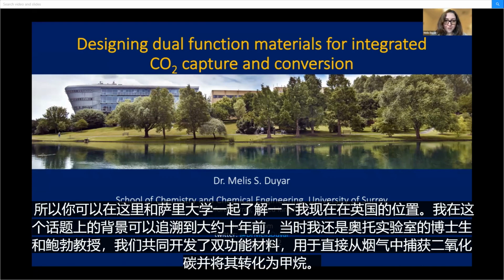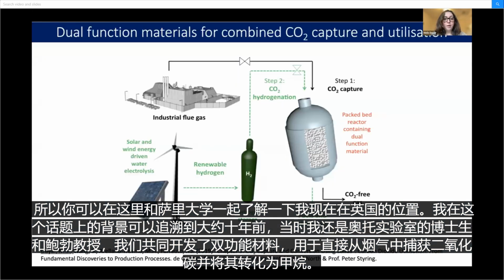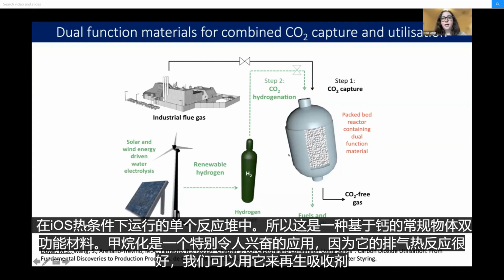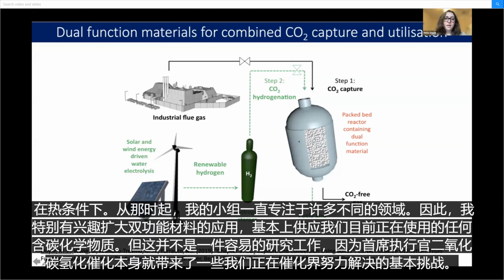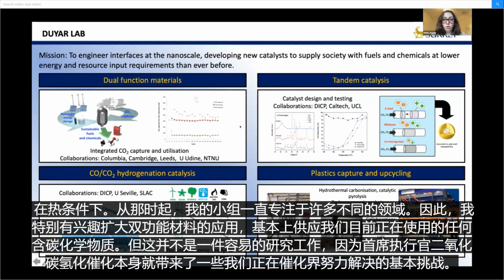So you can see here the University of Surrey, a little bit about where I'm located right now in the UK. My background in this topic goes back to about 10 years ago when I was a PhD student in Professor Bob Farrauto's lab. Together we developed the dual function material for capturing CO2 directly from flue gas and converting it to methane in a single reactor operating under isothermal conditions. So this was a calcium ruthenium based dual function material. Methanation is particularly an exciting application because it has this nice exothermic reaction that we can use to regenerate the adsorbent under isothermal conditions. Since then, my group has been focusing on a lot of different areas.